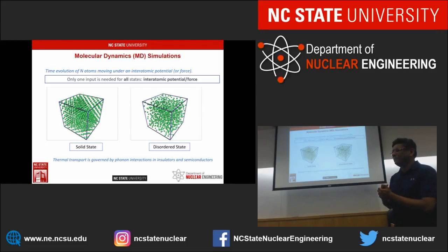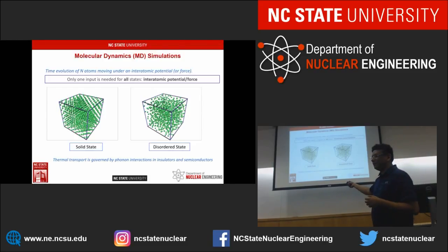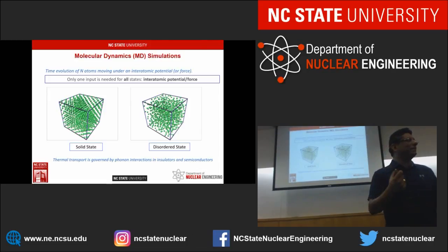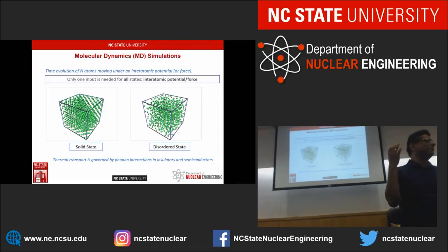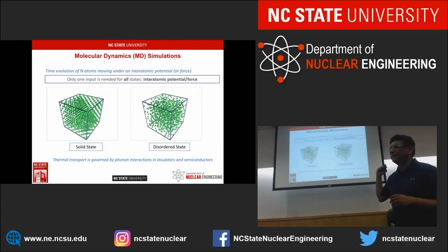So we would like to understand how atoms are vibrating, and from there we get phonon interactions and can compute properties like thermal conductivity. Thermal conductivity is important because there is no way to directly measure the centerline temperature of nuclear fuel — it can only be obtained through calculation, and that calculation needs material properties as input. This is where simulations are extremely helpful.